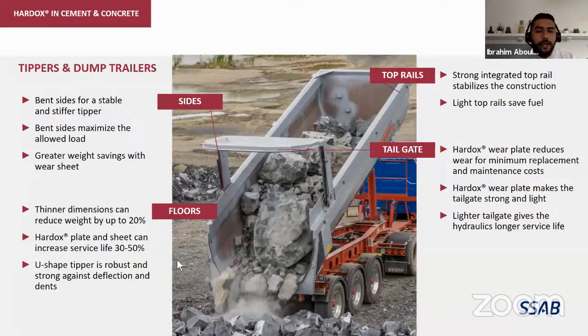In the floor, decreasing the thickness of the floor from mild steel to Hardox has alone around 20% of the weight savings. So the floor thickness reductions help a lot in the weight reduction. Then the service life will increase more or less from mild steel to Hardox 450 or 500 Tuf by at least 50%. And that case actually is between 450 and 500 tough. So if you take from mild steel to 500 Tuf, you have at least 2 or 3 times the service life of the tipper.